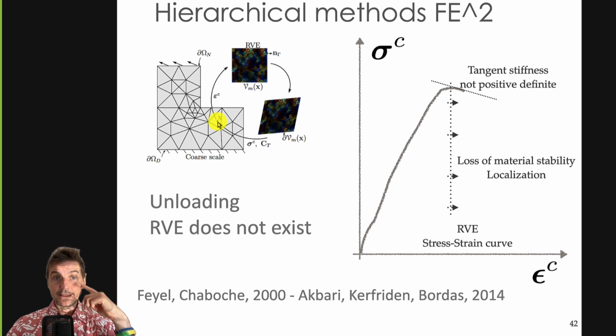When that happens, you need to find a way to regularize, and usually it's done by either a non-local model or a gradient model, or some higher versions of this, or you can introduce a cohesive crack directly here, which dissipates the amount of energy that you are dissipating. So you will introduce a crack, you will look at where you are on the down-going part of the curve, and with this energy below the curve, you will initiate a cohesive crack.